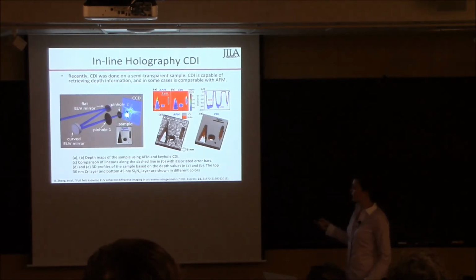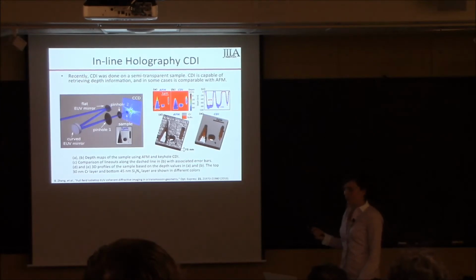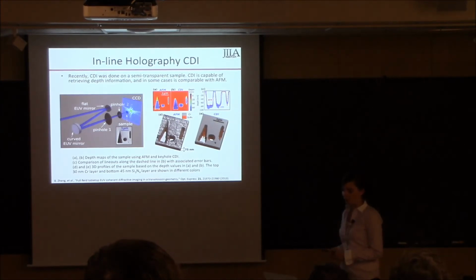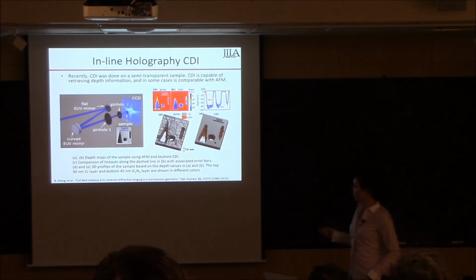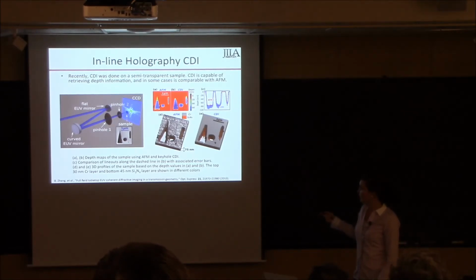You might notice that there's the addition of the second pinhole. And the purpose of the second pinhole is to reduce some scatter from the first pinhole. So it basically acts as a low-pass spatial filter. And the sample that was used for this experiment is chromium on silicon nitride with some holes punched through it and some shapes. So to test how well this worked, we compared it against AFM.